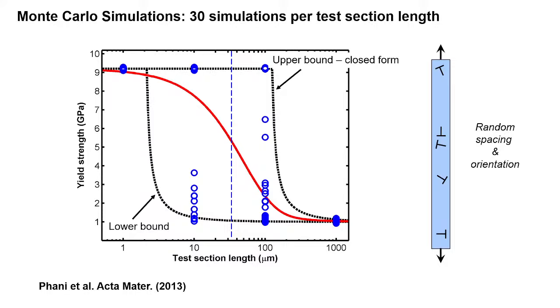And this is just the envelope of the upper bound, and this is the envelope of the lower bound, and all the data falls in this region. And now, when you take the Monte Carlo simulations and superimpose the experimental results, this is what you find. So where you would expect all the data to be clustered together is in fact where the experimental data cluster, and where you would expect them to be distributed in the middle region, this is where the data are in fact distributed.